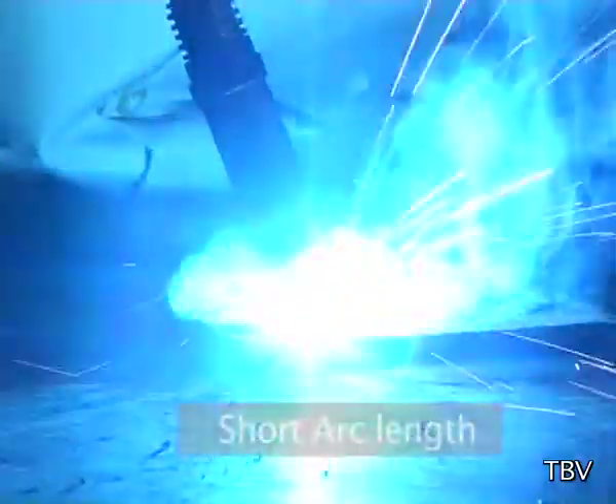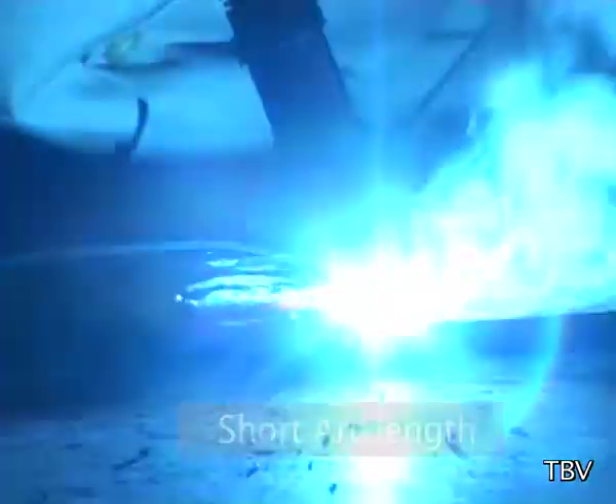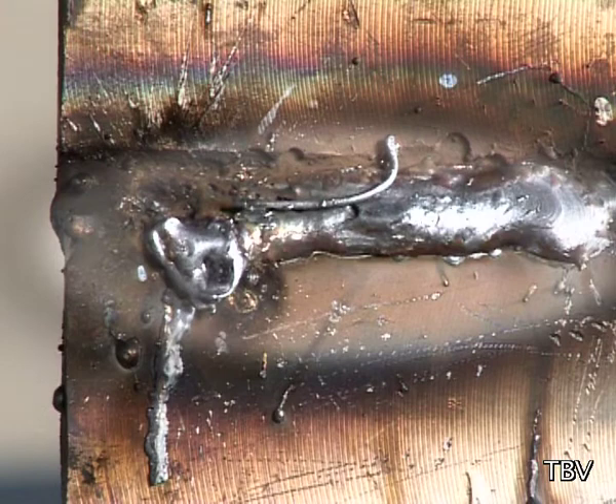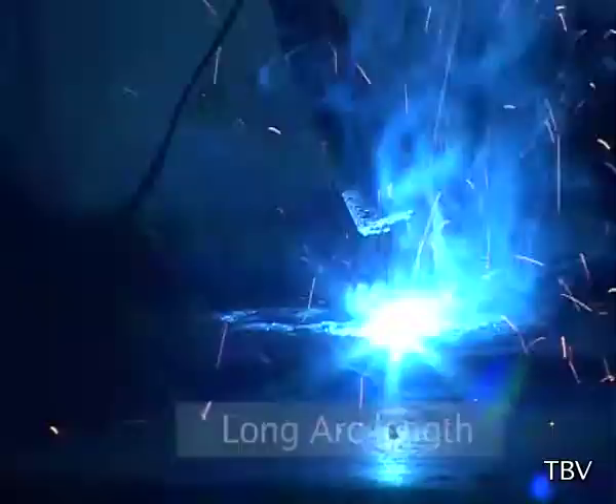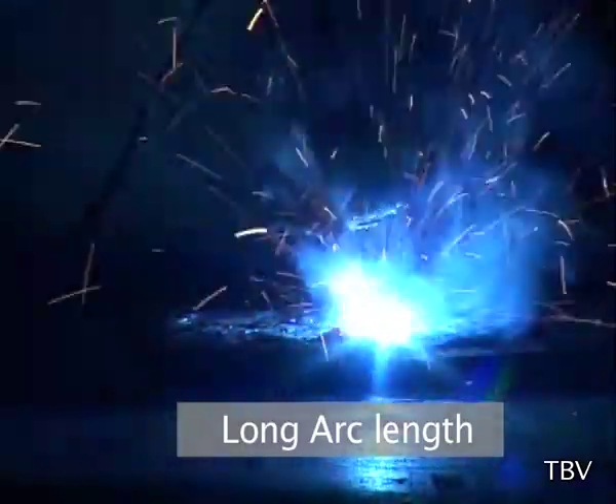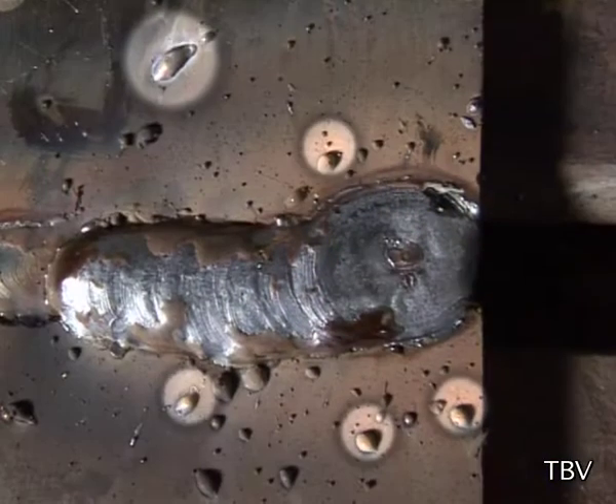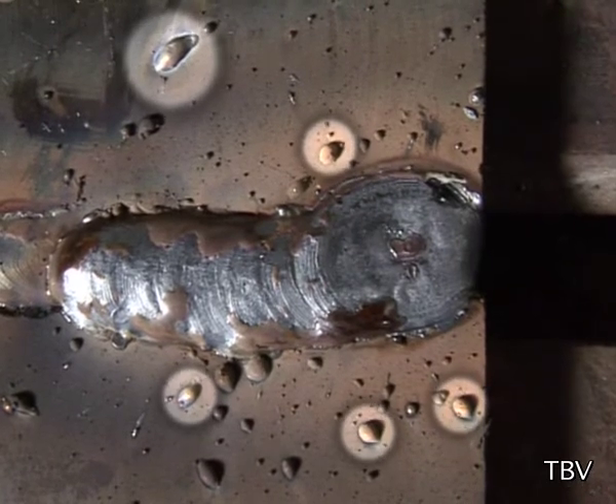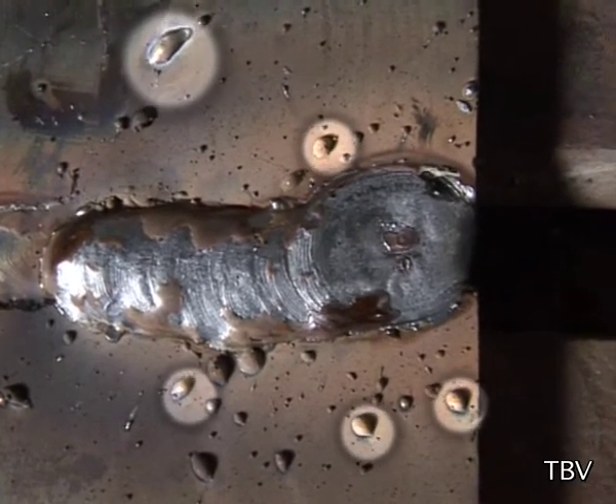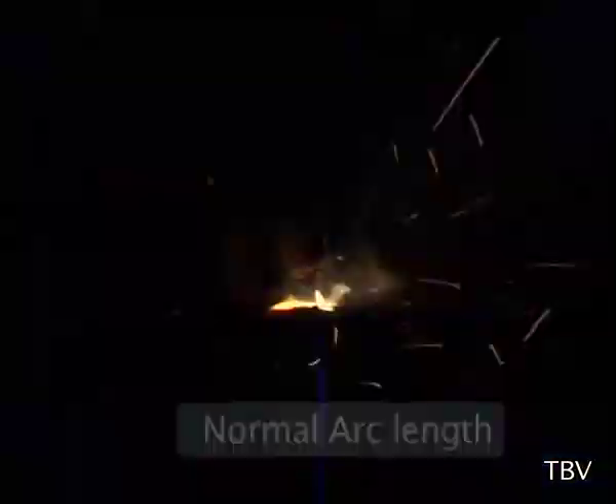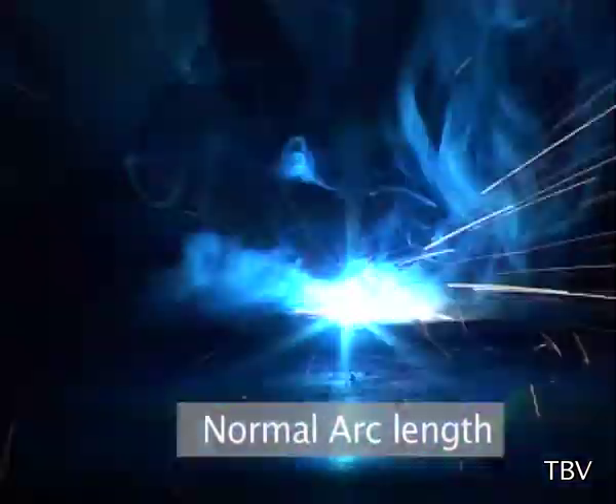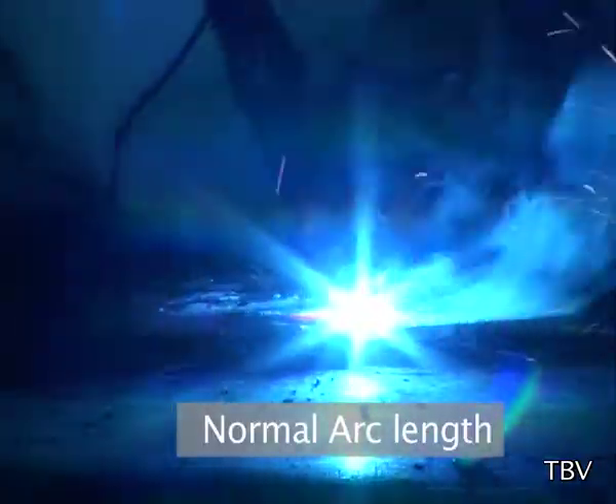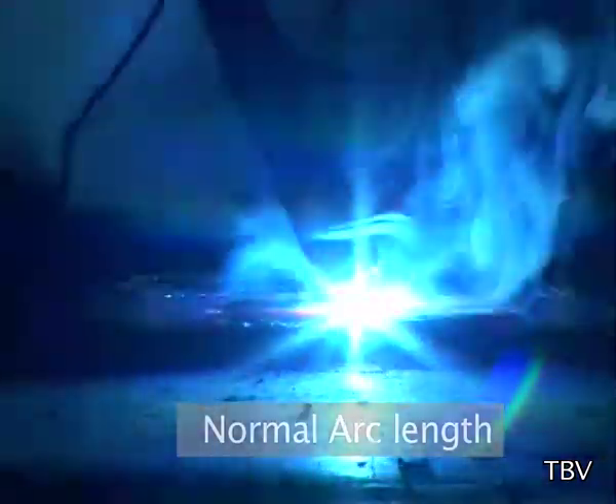If the voltage is too low, the wire sticks to the base metal, generating cracking sounds, and no arc is produced. If the voltage is too high, the wire burns, arc length becomes long, and much spatter is generated. It is also very important to maintain normal arc length of the gun. The wire speed is also maintained depending upon the material or metal thickness.